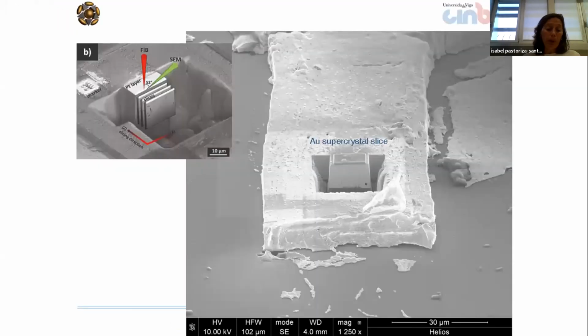And the point is that, as explained previously, the most intense areas for sensing are located inside the supercrystals. So therefore, we are very interested to know what the structure of this material is in the interior. To characterize that, we use focused ion beam combined with scanning electron microscopy.